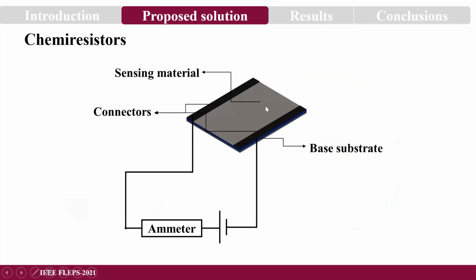The first one is the sensing material, which is the active component of the sensor. When analyte binds on top of the sensing material, the resistance of the sensing material changes, and this signal is picked up by these conductive connectors. We have a very small voltage supply. In our case, we generally use 10 millivolts as our supply, and we collect current as our output. As soon as the analyte binds, we see a resistance change, which is shown in the change in current of the sensor.